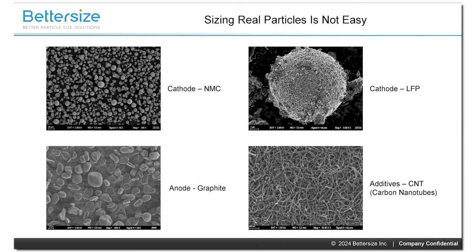If we examine some of these materials used in lithium-ion battery manufacturing, and here we have some SEM images, there are a few things to note. Here, the lithium nickel manganese cobalt oxide, you can see that we have a rather large particle size distribution, where we have round materials, but they're all of various diameters. If we look at the lithium iron phosphate image on the right, we can note that it has a non-smooth surface. On the lower left, we see graphite, and it's comprised of some very irregular shapes, as you can see. And of course, carbon nanotubes are non-spherical.